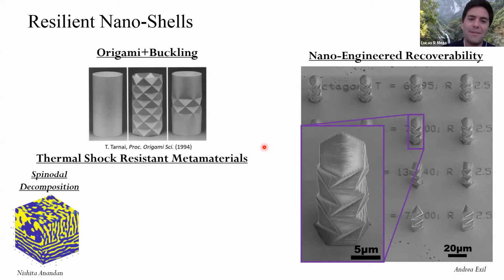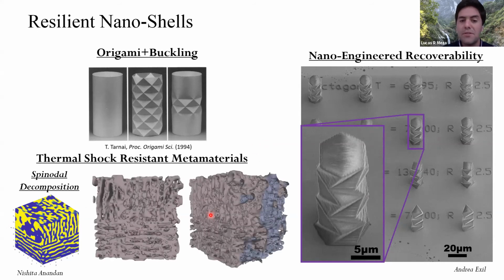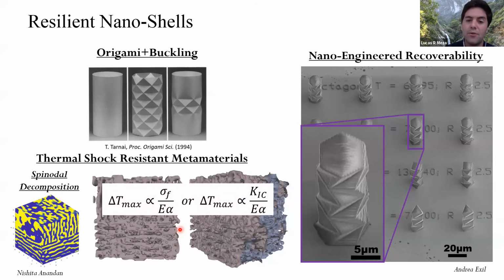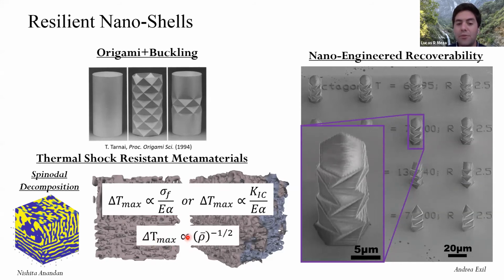In parallel, I'm running out of time, but I have another student, a postdoc who started working with me recently, Nishita, who's working on spinodally decomposed structures. Spinodal decomposition is a way around the cracking, particularly of sharp corners of lattices, by creating rounded out structures. A few groups have been working on spinodally decomposed structures, which are semi-random smooth surfaces. Nishita is actually working on creating gradient structures, with specific interest in creating thermal shock resistance into these. Thermal shock resistance is the ability of a material to withstand large sudden changes in temperature. It's governed by the thermal expansion coefficient and either the strength or toughness of the material, normalized by its stiffness. It turns out when you're creating ultra lightweight materials, you actually get a benefit to your thermal shock resistance.